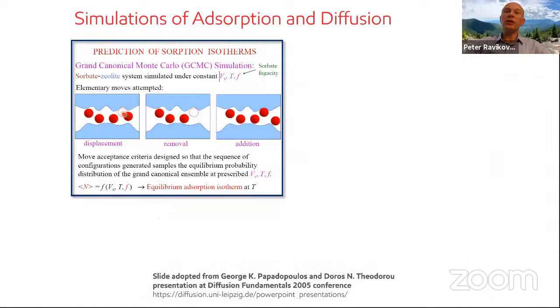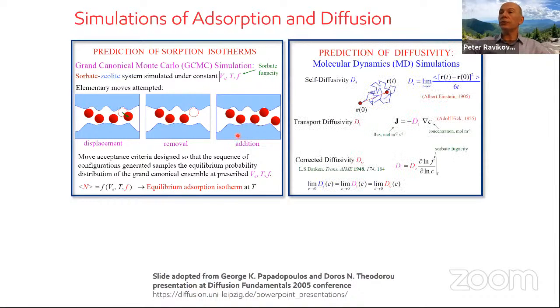Again, for simulating adsorption isotherms, we use so-called grand canonical Monte Carlo simulations. We use displacement, removal, and addition of molecules. For simulations of diffusion, the method is molecular dynamics, where the Newton equations of motion are solved for all the atoms, and then trajectories of the atoms can be used to calculate the so-called self-diffusion coefficient according to the Einstein relation. Molecular dynamics simulations can be performed with a flexible structure if the force field is available.